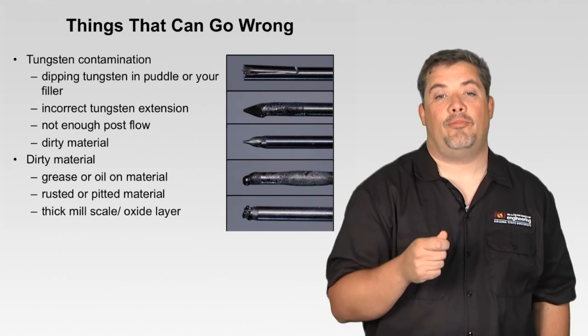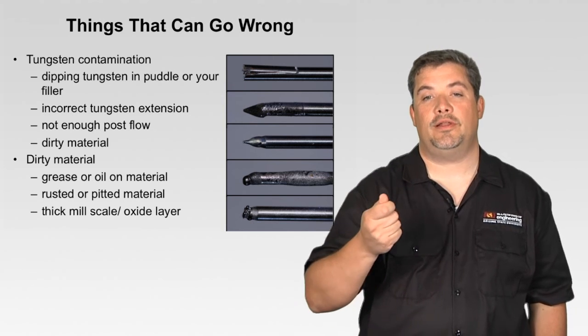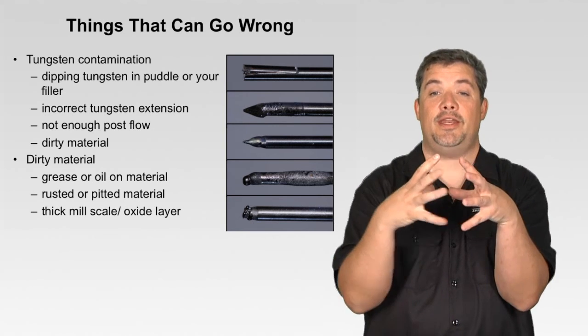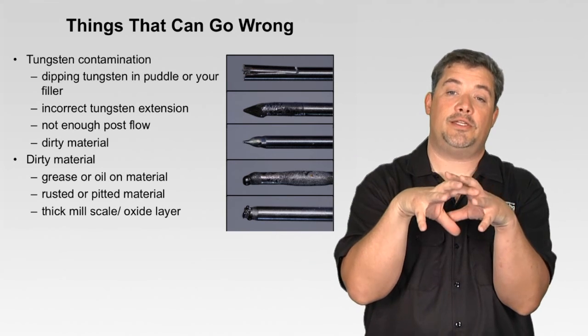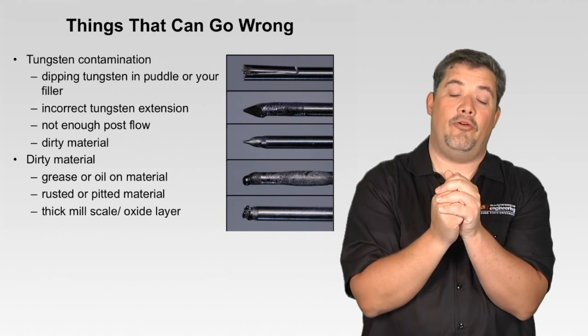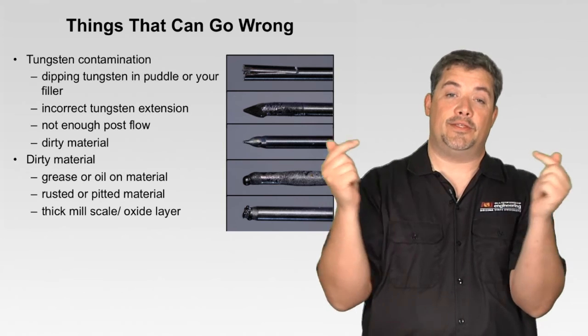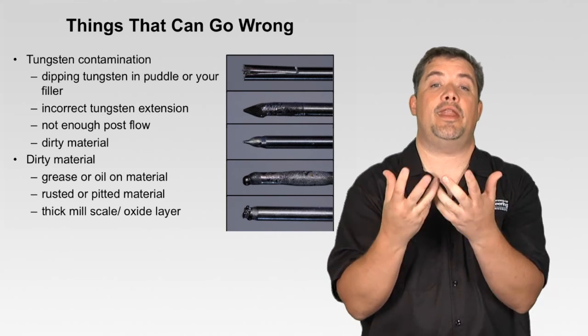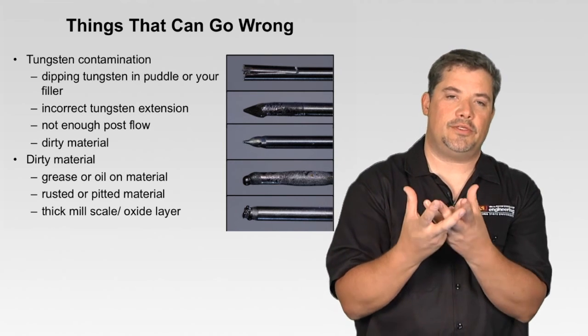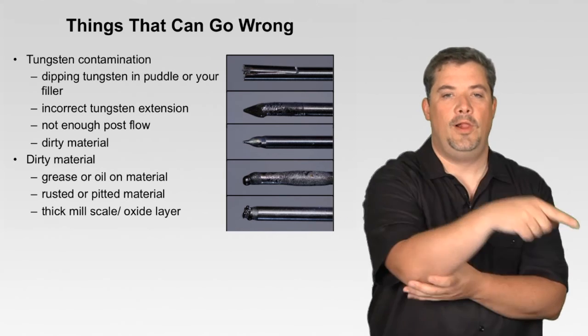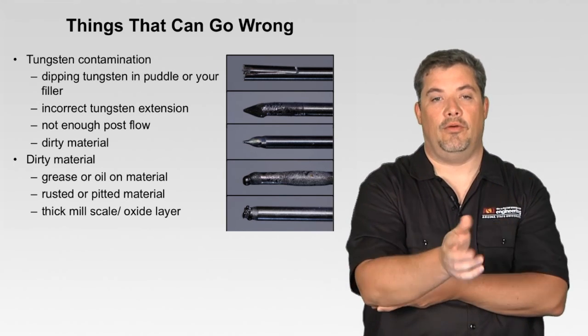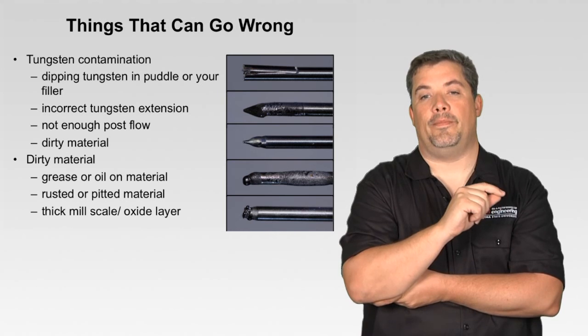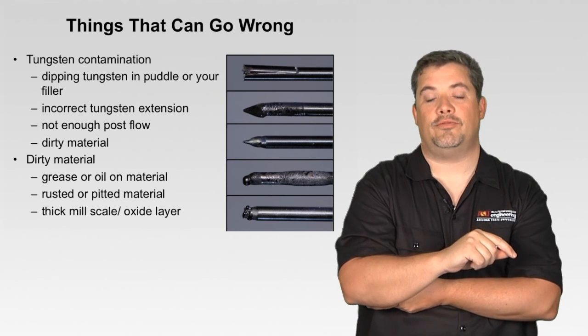Not enough post-flow is a bad thing as well with tungsten, because the tungsten is elevated in heat, and if that tungsten isn't allowed to cool enough before the atmosphere hits it, the surface of that tungsten gets contaminated, and now you're potentially introducing those contaminants into the weld pool, creating a less than sound weld or a rejectable weld. So making sure you have enough post-flow is huge.